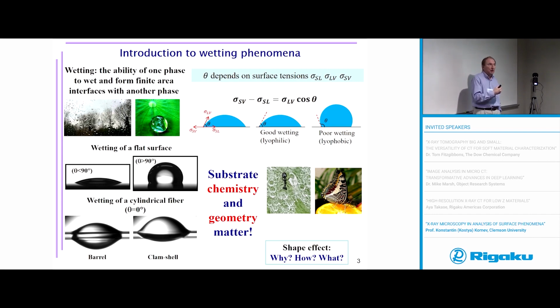So, the industry tries to defeat that paradox using very simple material and making the material work as hydrophilic, even if the chemistry is supposed to be hydrophobic, or vice versa, right? And I will show you the trick how to do that. And the big difference between that ideal situation and the real situation: we saw excellent tomography images of the fibrous material. So if you have a drop and that drop is placed on the fiber, you will be amazed that even if the material is completely hydrophilic, zero contact angle with a flat surface, on that fiber the drop is going to be beading, making it impossible to wet the fiber completely, right? And that is a very interesting trick that nature is using all the time.